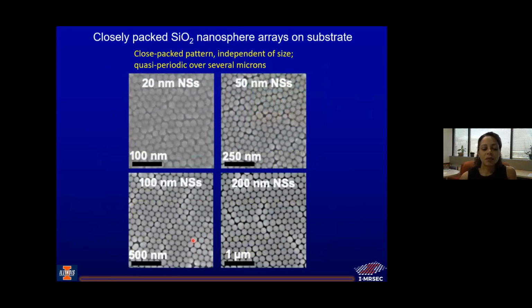Okay. So here, I believe these are SEM images of nanospheres on our substrates. And you can see that we get these close packed patterns independent of size that are quasi-periodic over several microns. So on the left here is a 20 nanometer array, and you can see that you get this kind of quasi-periodic pattern, 50 nanometer, 100 nanometers, and 200 nanometers. Okay, and you can also see that there are some defect lines in here. So you get this quasi-periodicity over the scale of, say, a couple microns. Okay, so if we have a device that's, say, 2 microns wide, we might expect 1 or 2 crystalline domains within our device. Okay, but otherwise they look pretty nice, as you can see, and they're pretty uniform on the scale that we're talking about.